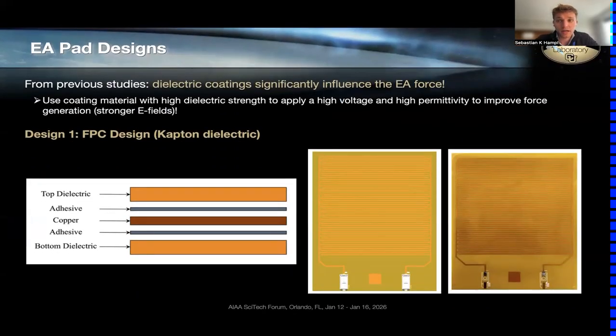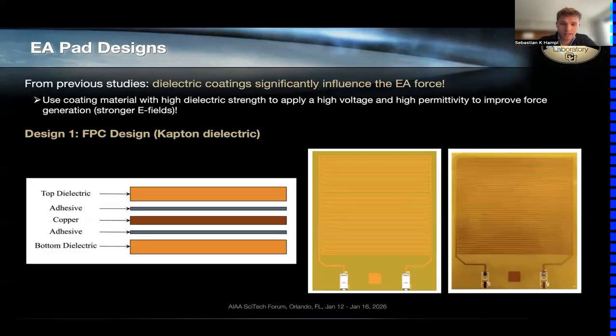So the standard way of constructing an electroadhesion pad is using flexible printed circuit boards. This means we have the two electrodes sandwiched in between two copper sheets, and there's some adhesive that is holding this all together. So what is known for electroadhesion pads is that we would like to get coating materials that have very high dielectric strength to apply very high voltage and generate a stronger force, but they should also have high permittivity to let the E fields through. Kapton excels on the dielectric strength, however, does not have the high dielectric permittivity. However, this is the simplest and cheapest option to mass produce electroadhesion pads.